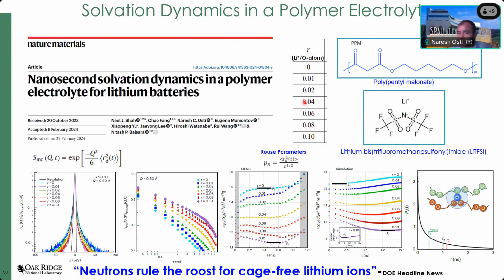As you can see, we use from no salt concentration all the way to 0.1 concentration. Those concentrations, R, is the ratio of the lithium contacting with the number of oxygen atoms present in the monomer of this polymer.